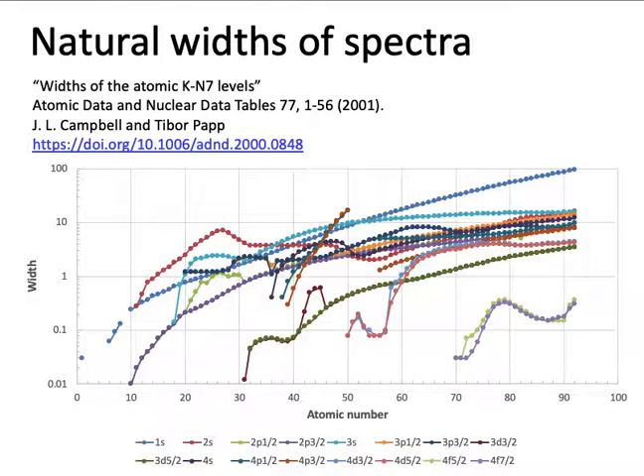XPS peaks also have natural widths, because each excited electron has a finite lifetime that depends on the binding energy. At higher binding energy, the lifetime is shorter, because the excited state returns to the ground state very quickly. At lower binding energy, you have a longer lifetime, so you can obtain much sharper peaks.